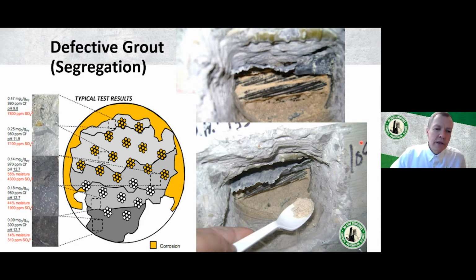Another issue that definitely can lead to problems is segregation, which in extreme cases could lead to soft grout. A lot of agencies have moved from using cement water grout to using prepackaged grouts. These grouts have additives to prevent bleed or to greatly limit it, and that's good. But if you add too much water to those mixes, or in some cases, maybe if the bags are a little bit old, you can have segregation occurring. And that's simply a separation of the material based on density. You'll have denser material at the bottom of the duct, and the lighter material will float to the top.